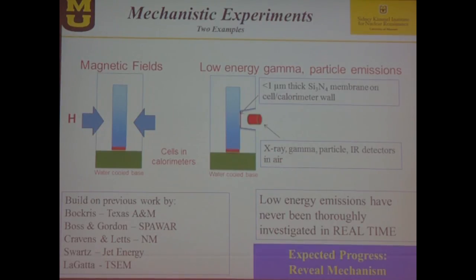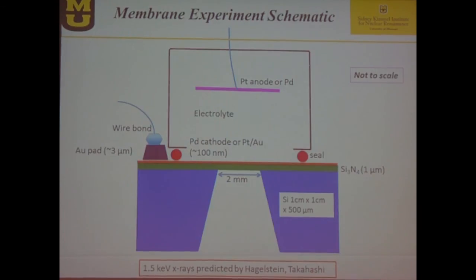So far, although we are running those experiments, we didn't see any X-ray emissions. But we are continuing. We will do the same thing with magnetic fields, with permanent magnets as well as electromagnets. And this is how it looks. As I said, either it's a platinum anode with an electrolyte, like palladium sulfate dissolved in the solution in order to build a layer of palladium in situ on the membrane. This is the silicon nitride membrane, and the detector is here. Or, as I said, replace the order and put the anode as the palladium and the platinum as the cathode, and get the deposition of palladium in situ.